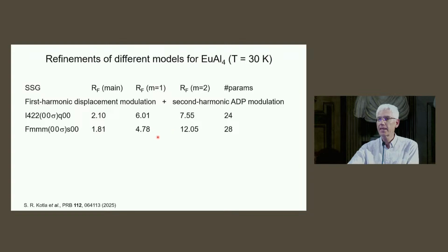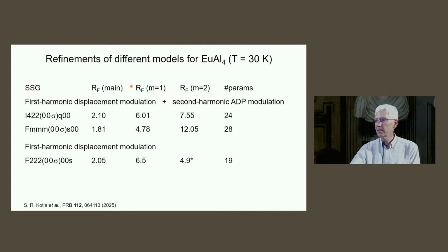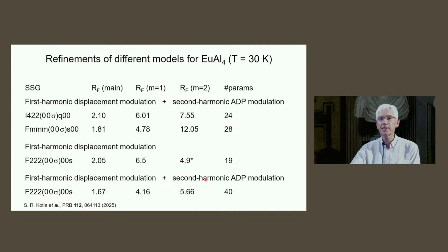And we tried the non-centrosymmetric groups. This is what I showed before. And now we removed this second harmonic modulation of temperature parameters, and we get something which is a clear improvement, but still with two problems, higher than the basic structure, and this problem is calculated too strongly, and that's then repaired by the second harmonic temperature factor modulation. This is good, and that is suddenly much better than the basic structure of 1.81.